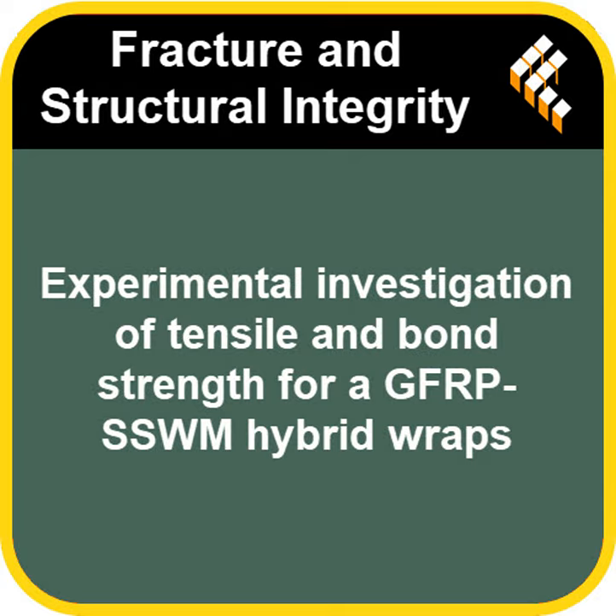And the hybrid, that's the sweet spot. The hybrids GS, SGS, GSG showed significantly better deformability. Give me an example. Okay. The GS configuration, with Sikadur 30 LP again, showed about 73.88%, to be precise, higher displacement at failure than the pure GG specimens. So it stretched almost 75% more before breaking. Yeah. It means it gives you more warning. It bends more before it actually fails, which is often safer in structures. That makes sense. More forgiving.